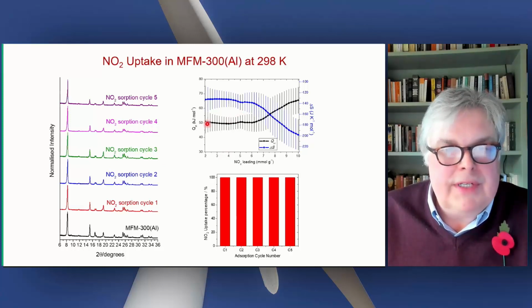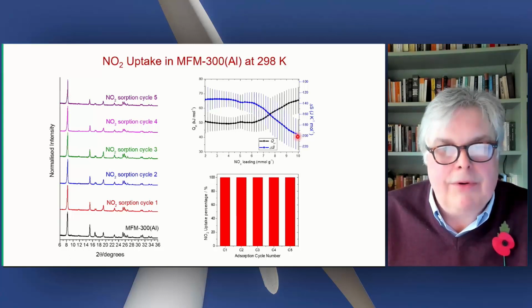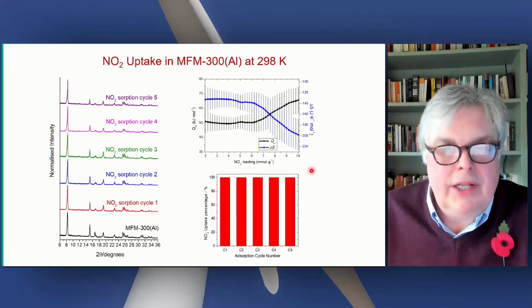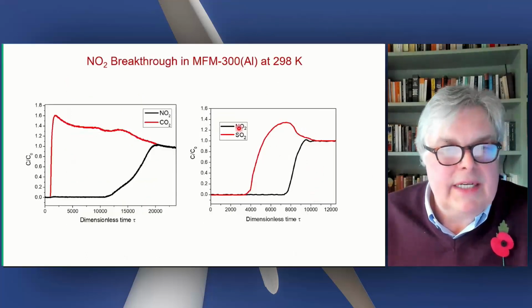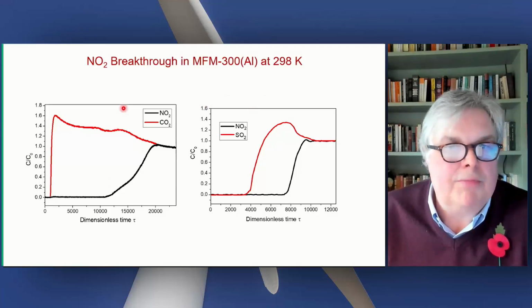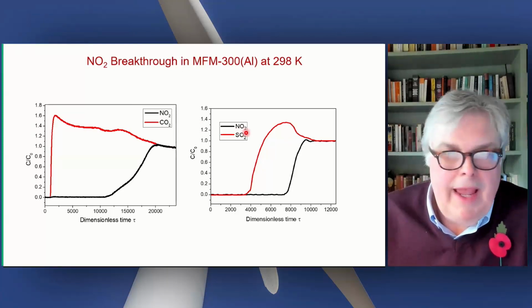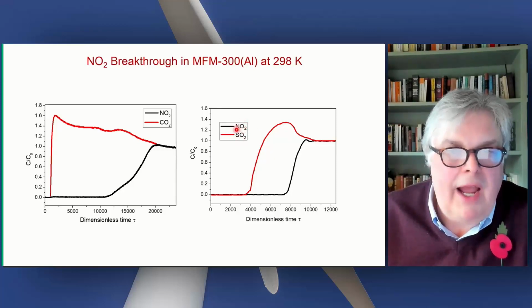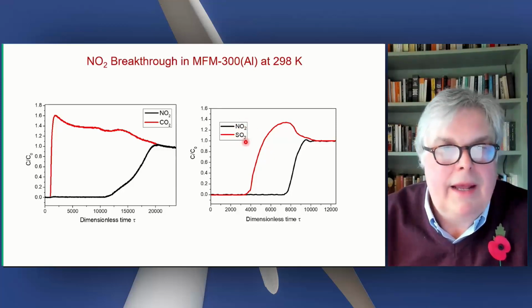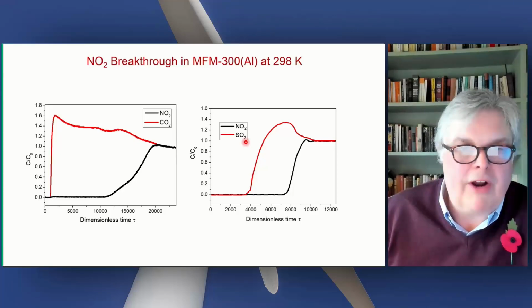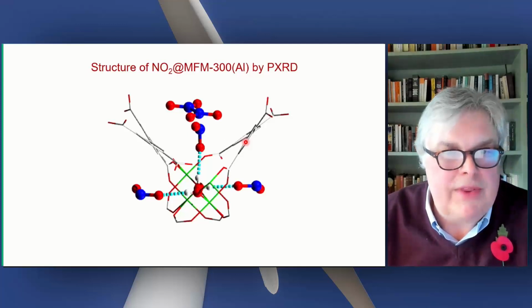This is a plot that we often show, this is plotting the enthalpy. The enthalpy goes up as you load up NO2 and the entropy goes down. So that indicates NO2-NO2 interactions as you load up. And this likewise suggests greater ordering as loading goes up. This is reflected in the structure, which I'll show in a moment, but this is the NO2 breakthrough, NO2 with CO2, NO2 with SO2. So you can separate these very noxious, highly reactive, highly corrosive materials within a very stable aluminium metal organic framework. There were complications with this structure.